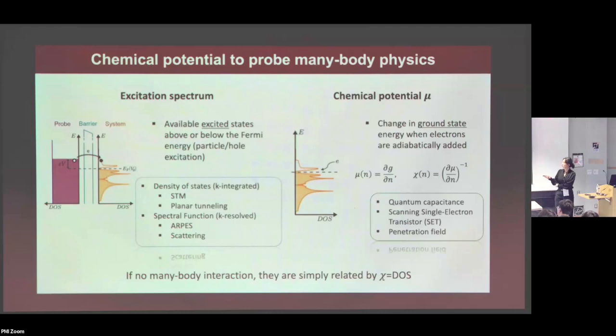Okay, so before going into the details of the experiment, I still just want to give you an overview. Typically, when we try to study some sort of many-body physics in these material systems, there are two different routes in terms of learning about that. One is the excitation type of measurement, where you're trying to probe the available excited states above or below the original Fermi energy. That includes the techniques that we're familiar with, like STM, ARPES, scattering, and all these excitation type measurements. But there's a complementary approach where you can measure this quantity called chemical potential. Instead of trying to probe the available states, you're directly tracking the ground state energy itself as your electrons are adiabatically added or removed from your system, okay?